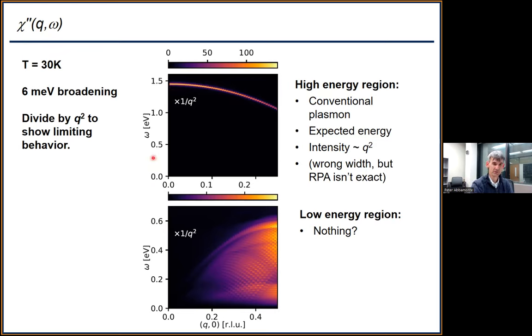So if you look at the high energy region, then you expect to see a plasmon, and there it is. And it's at around 1.5 eV, which is similar to what we see in the experiment. The width is really narrow, much narrower than the experiment, but we already know RPA doesn't give lifetimes and things. But it tells you the right number of modes and it tells you the rough energy. So there it is, everything's good. And then we thought, okay, let's look down at low energy now and see if there's a demon. And that's what this is.